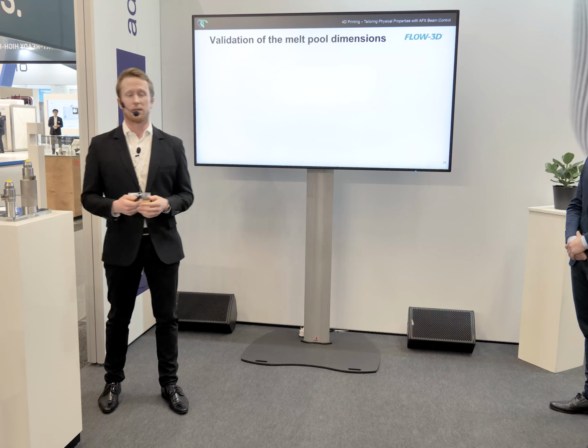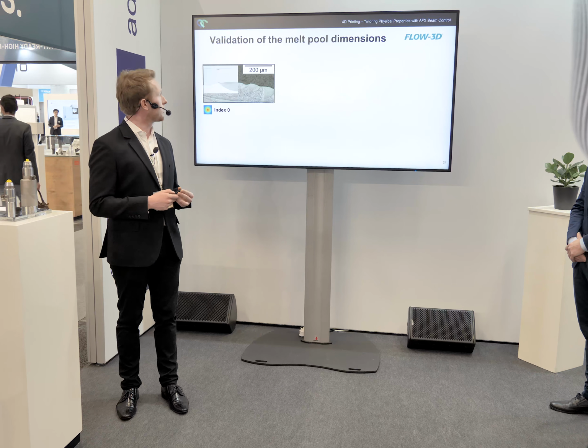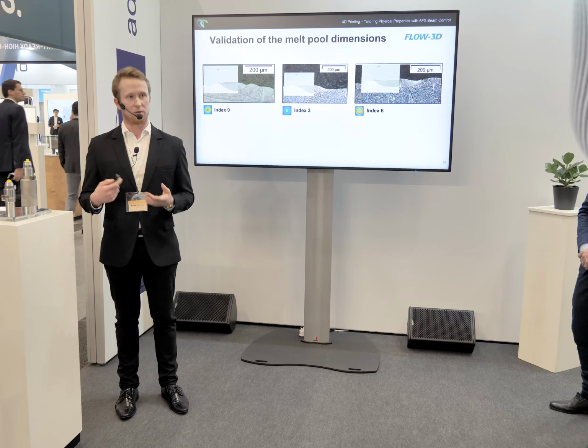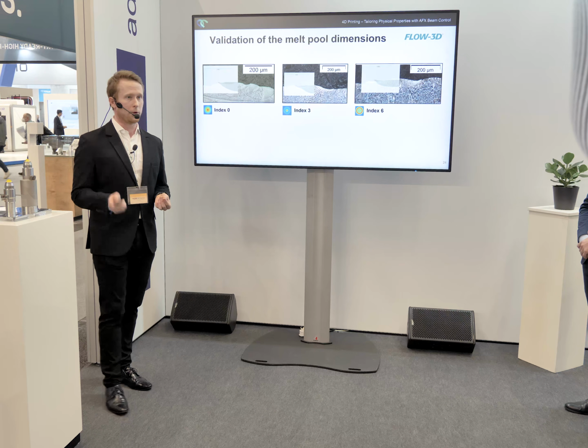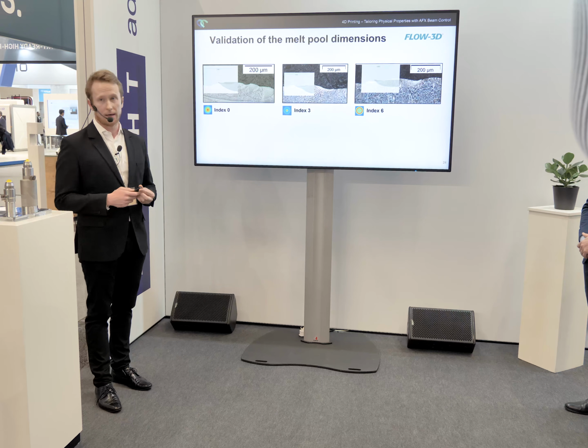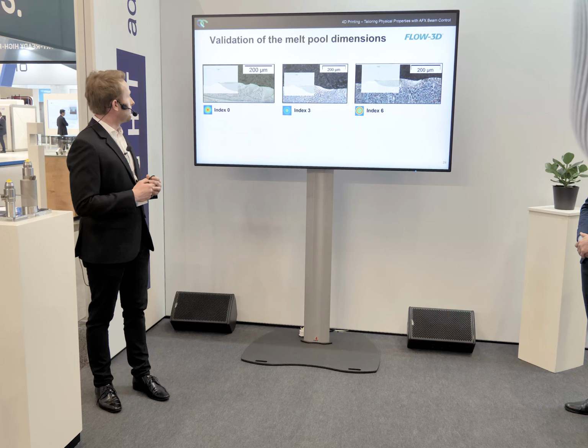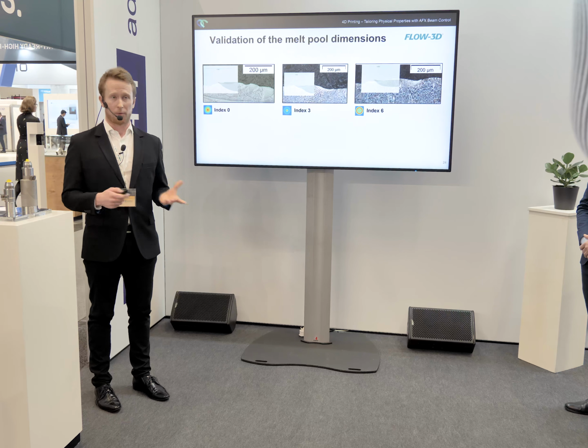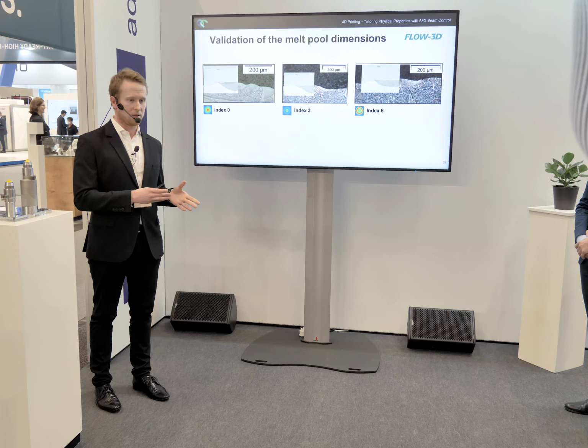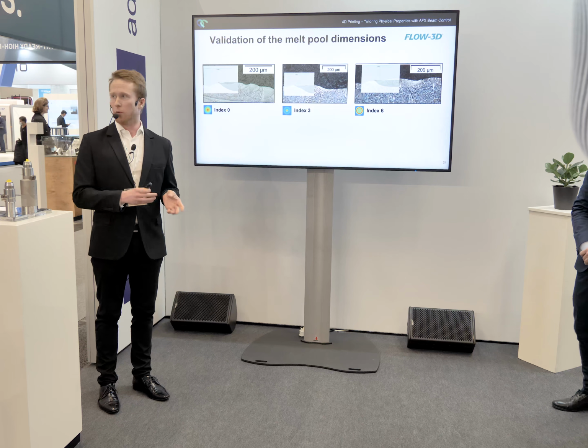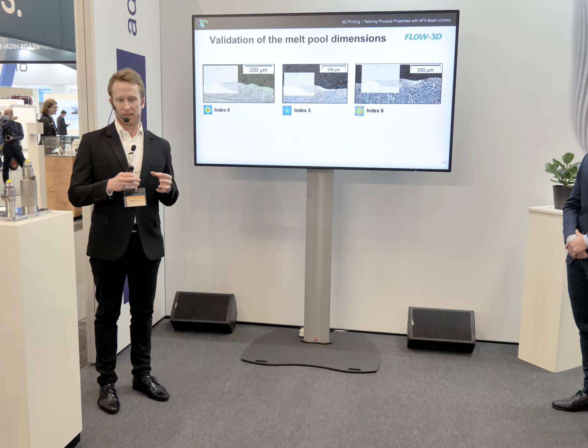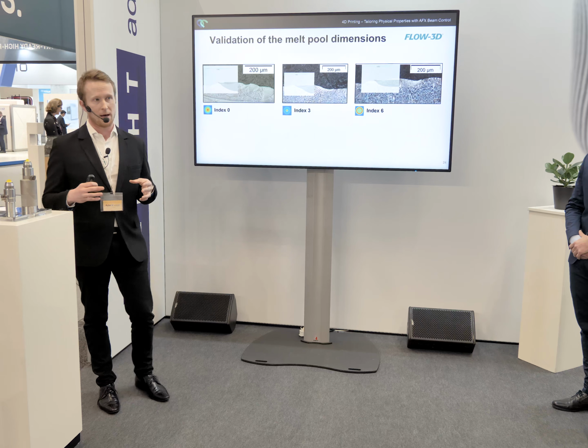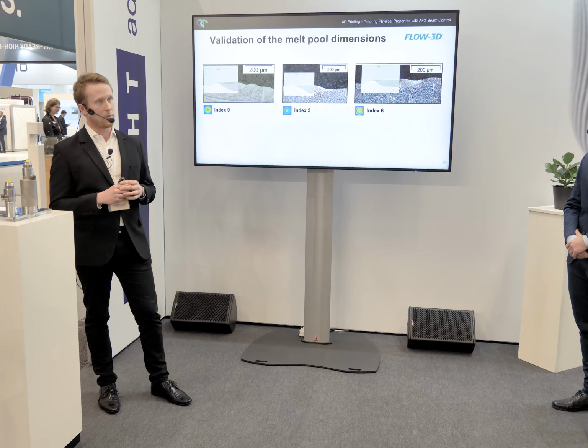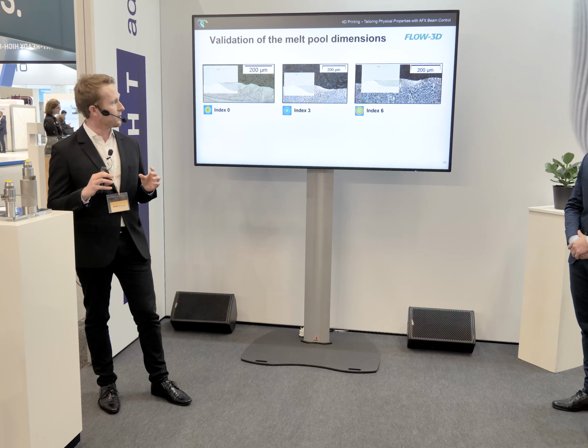So first of the results slides, here I would like to show you the comparison between the cross-sectional shapes of the melt pool from the model together with the experimental results. What we can see here, what Marco has already mentioned, is that when we change this heat flux distribution by moving the amount of heat from the center to the outer ring of the laser beam, the melt pool shape becomes wider and shallower.